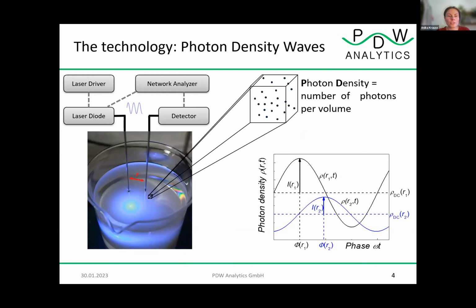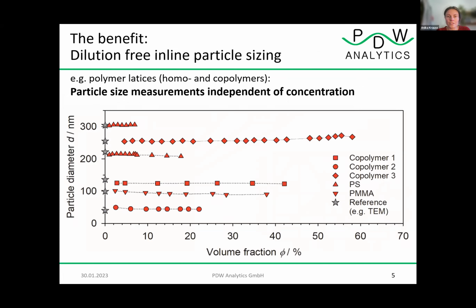This is how the instrument basically works. We have laser light, which is guided through an optical fiber into the material. There it creates, through multiple scattering, the so-called photon density wave, which is detected by a second optical fiber after a specific distance and then analyzed. Based on the intensity and phase difference between the emitting and the detected fiber, we can then derive the scattering and the absorption characteristics of the material.